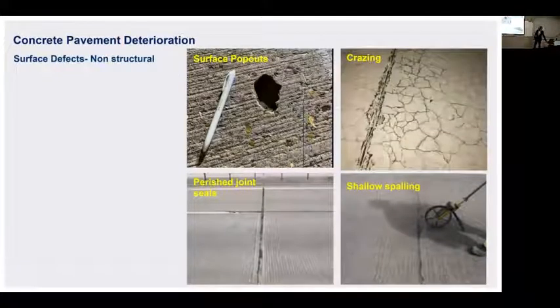And apart from the structural ones, there are also other defects. These ones are very minor surface defects. You can expect to have surface pop-outs, crazing, perished joint seals and some shallow spalling. There are lots of different reasons for it. For crazing, for example, if you have early bleeding in your concrete mix, poor compaction or even curing issues, those can contribute to both surface pop-out and crazing. For perished joint sealant, it's mainly the age of the sealant material. If it's not replaced quite often, that could lead to issues. Shallow spalling is mainly a superficial defect.